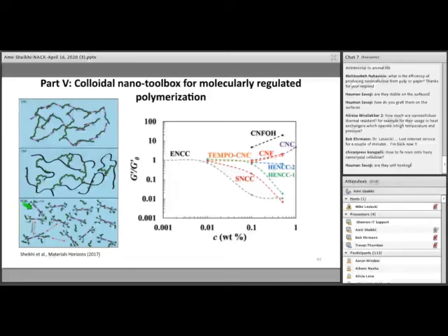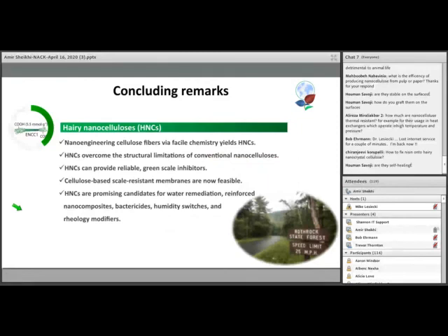by increasing the concentration of these hairy nanoparticles, the storage modulus decreases, meaning that they prevent or impair the formation of the network, because the early stage monomers adsorb on these hairs, and then the electrostatic and steric repulsion between these hairy nanoparticles keeps these monomers separate from each other, preventing the formation of a strong network. And this can be used for developing highly soft hydrogels for a variety of applications, such as oral drug delivery